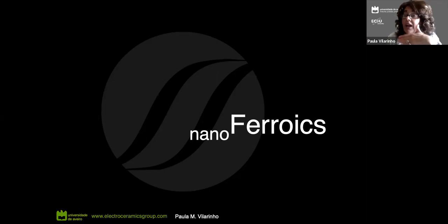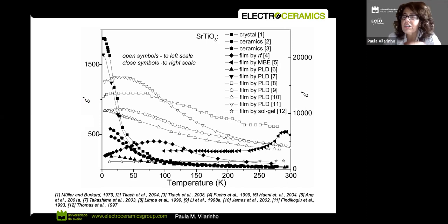just to tell you that I do believe that some of these materials will be relevant in these systems. So my first slide, although this slide looks a little bit complicated, and maybe indeed it's a little bit complicated. So this is the dielectric permittivity that I mentioned before, that I presented. So this you can read as a synonymous of polarization as a function of temperature. So there's a mess here. There are these black curves, and there are these open curves. So what I want to show you here is this is the dielectric permittivity as a function of temperature behavior of a very famous material, important material in microelectronics, strontium titanate.